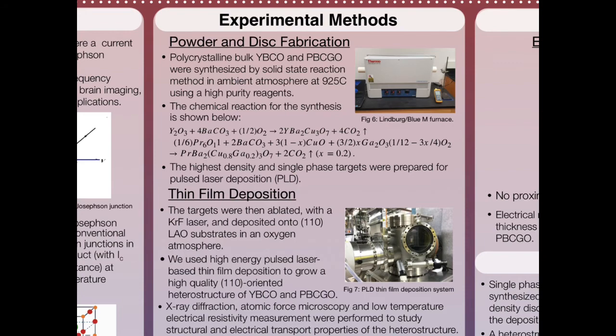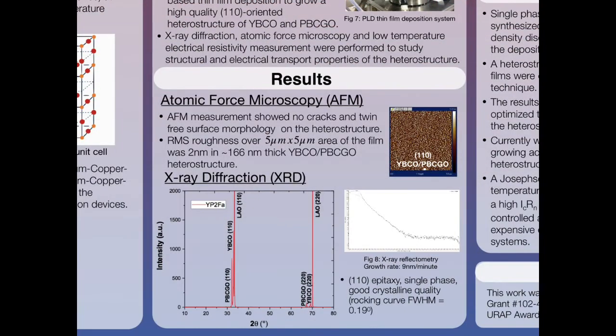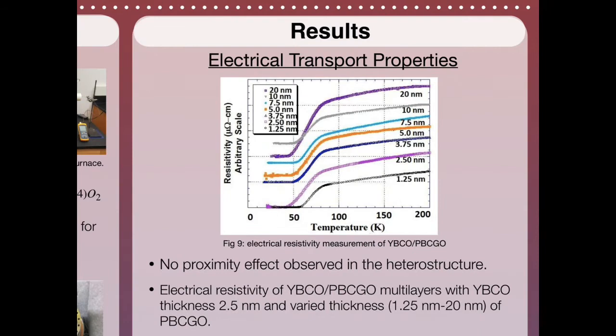After fabrication of the bilayer, or heterostructure, was completed, we conducted many tests to measure its lattice structure, surface morphology, and electrical properties. The atomic force microscopy measurement shows about 1 nanometer root mean square roughness in our heterostructure, and additionally it contained no cracks on the surface of the film. The low-temperature electrical resistivity measurement showed the critical temperature value of the heterostructure to be 82 Kelvin, which was close to the TC value of a single layer of YBCO, thus demonstrating no significant proximity effect.